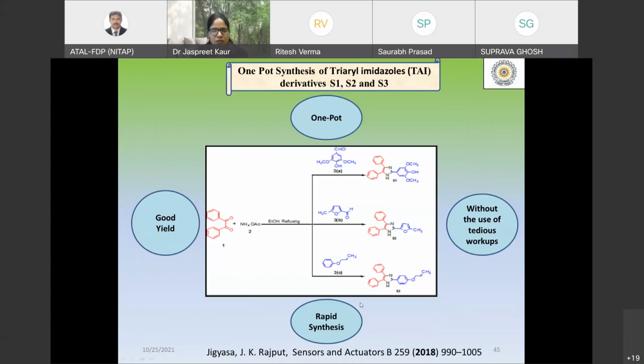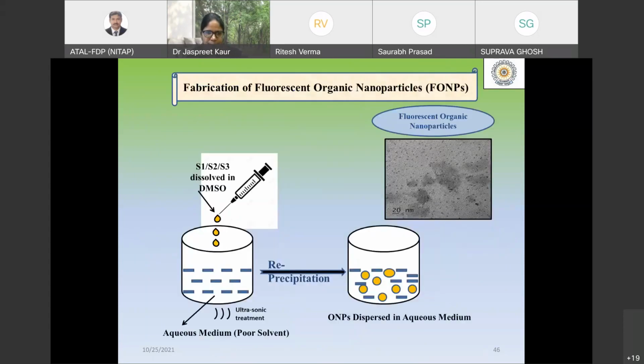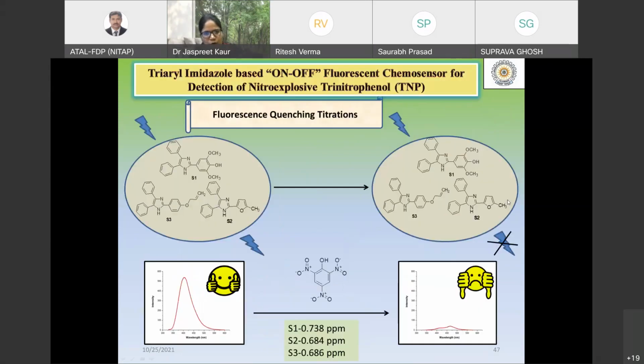So these organic nanoparticles have been synthesized from the triaryl imidazole, TAI, derivatives. These derivatives have been synthesized by a single one-pot synthesis. We have synthesized 3 different compounds, S1, S2, S3. It doesn't require tedious workup, and the synthesis was one pot and rapid. So they can give you the fluorescent organic nanoparticles.